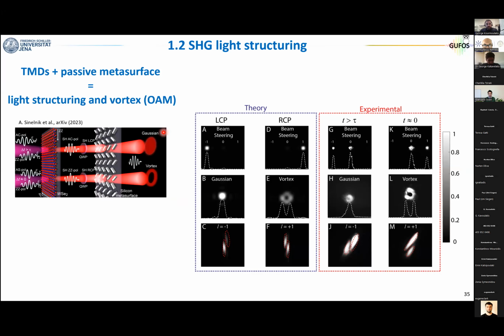And it turns out, this is something that we did in collaboration with Isabelle Staude in Jena, that if you have an ultra-fast half-wave plate, that is our TMD in the nonlinear optics regime, and you combine it with a passive metasurface, then this total optical element can be used to tune the wavefront of light. So now we can play with this device to achieve, on an ultra-fast timescale, beam steering, Gaussian to vortex beam tuning, but even tuning of the orbital angular momentum. So these nonlinearities of the TMDs are also very powerful if you then want to combine them for complex light structuring and light shaping.